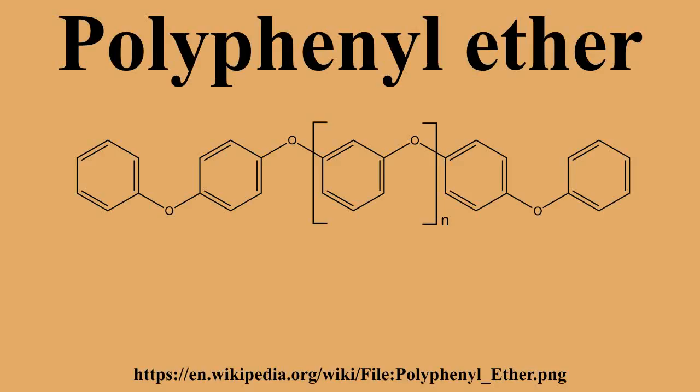Polyphenylene oxides. These polymers are made through oxidative coupling of substituted phenol in the presence of oxygen and copper and amine-containing catalysts, such as cuprous bromide and pyridine. See Figure 2 for the PPO structure. PPO polymers can be classified as plastic resins. They and the composites with polystyrene, glass, and nylon are used as high-strength, moisture-resistant engineering plastics in a number of industries, including computer, telecommunication, and automotive parts. PPOs are marketed by SABIC Innovative Plastics under the trademark name of Noryl.